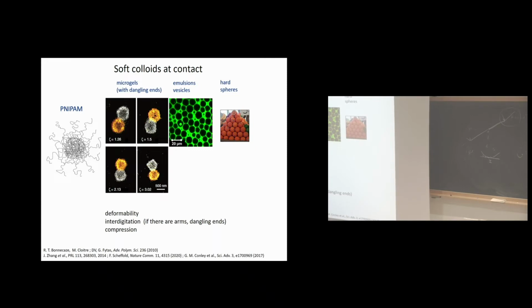And in these images, one can make some observations. This is increasing the effective volume fractions. So you can see that there is certainly some regime of interdigitation because of these outer layers. And this becomes even more apparent here. But then, of course, you can see that there is faceting. Obviously, for clarity, only the two particles are shown. You can see the facets which are formed, right? And then, of course, you can see that there is compression as well, because this is smaller than this one here, right?